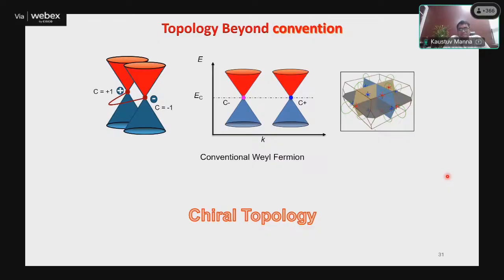Next is very, very important, on which I want to spend 5 minutes. This is chiral topology. As I said, I am a co-discoverer of this chiral topology. So why it is so exotic, why it is so important, let me explain a little bit. In the conventional Weyl semimetal, whether you take magnetic or time reversal invariant, non-magnetic, like 99% of materials, you always have a mirror symmetry. Because of this mirror symmetry, these Weyl points appear at the same energy in the dispersion, E(k).